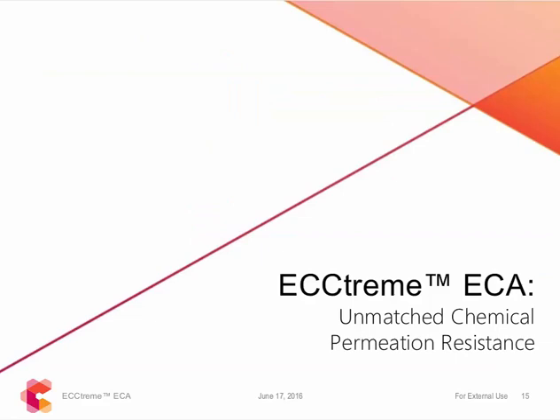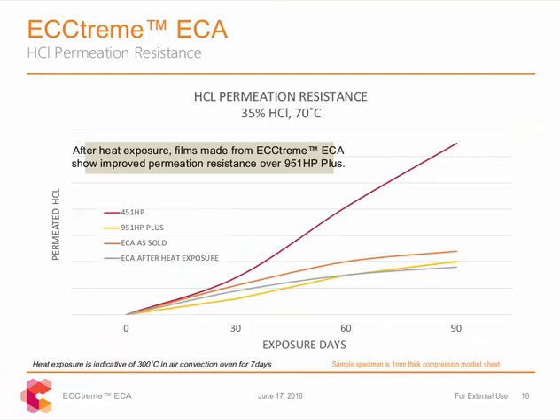While high temperature resistance and physical property retention are obviously critical properties for an insulating material, resistance to chemical exposure and chemical permeation is paramount in many high temperature applications like downhole and geothermal. So we also have some data to share showing ECA's superior performance in chemical applications as well. Along with evidence of excellent general chemical and steam resistance, ECA's unique co-crystallization effect that I've mentioned a couple of times increases the permeation resistance of the material, giving it the ability to outperform some PTFEs and low permeation PFAs. An example shown here is exposure to concentrated HCl, hydrochloric acid, at elevated temperatures.